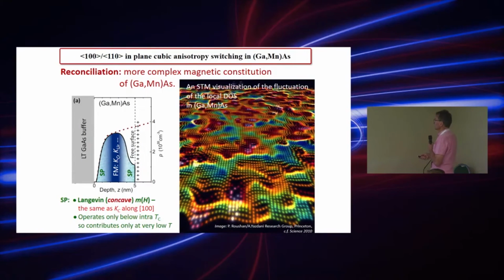In this very nice representation, each dot is an atom, and the colors correspond to the density of states. So we've got low density of states here and large density of states over there, and you see that at the surface of the material, the landscape is very complicated. The ferromagnetic coupling is maintained only in these red or brown regions, where the hole density is high enough to support ferromagnetic coupling. There is no ferromagnetic coupling whatsoever in these places, because there are simply no holes.